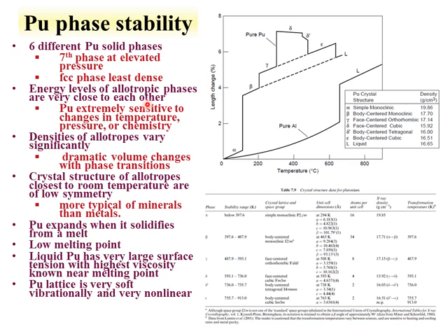All these phases are close to each other energetically, so that's why they can be reached through just heating the sample. Then the densities of these phases vary dramatically. The data is shown here, where the most dense phase is the alpha phase, which is close to 20 grams per milliliter, and the least dense phase is this delta phase, the face-centered cubic, or FCC phase, where you get a little bit under 16 grams per milliliter.